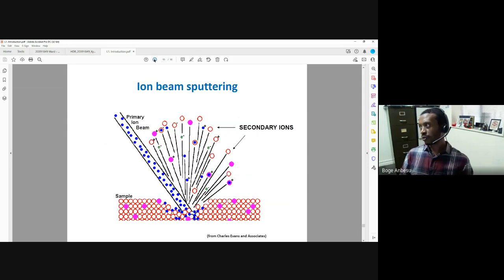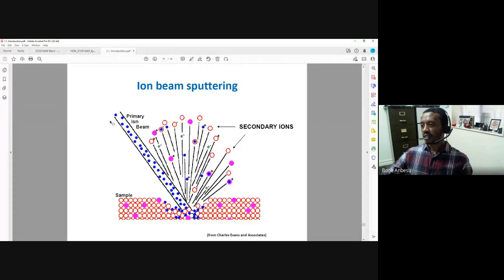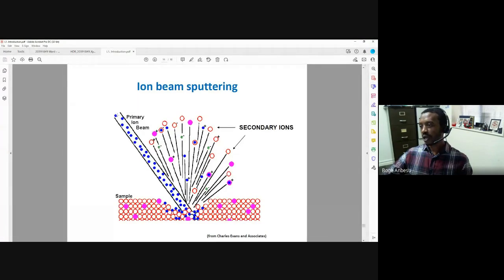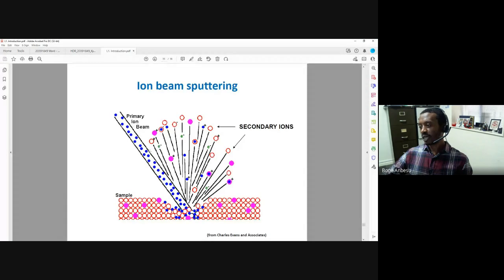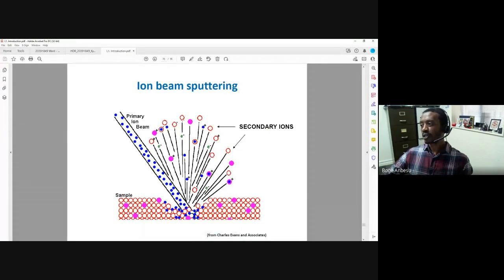Maybe this picture will tell you what's going on a bit more clearly. So here you have a cesium ion or an oxygen ion coming, as a primary beam, hits the sample, literally makes a fragment from the sample, producing lots of secondary ions. If I have gold, what should happen? I should have gold fragments or gold secondary ions fragmented from the sample. If I have sulfur, I should have sulfur ions coming off the sample. If I have iron, there should be iron species coming off the sample.